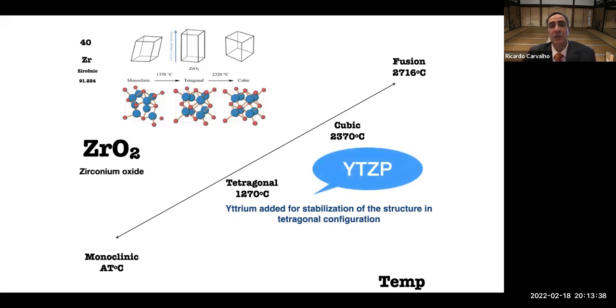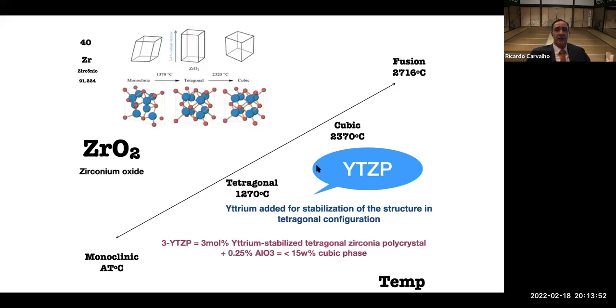And that's where the actual name of the zirconia comes from: yttrium-stabilized tetragonal zirconia polycrystal. That's the name of the zirconia that we usually use. It's also usually referred to as 3Y-TZP, which contains 3 mole% of yttrium. This zirconia polycrystal usually has about 0.25% of aluminum oxide, which is what gives the strength of the material and also the opacity.